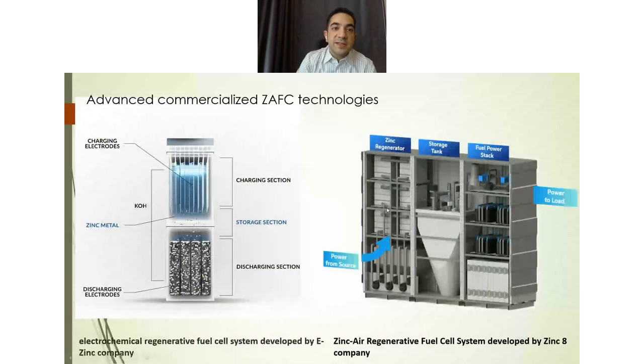There are some advanced commercialized zinc fuel cell technologies with different ideas of operation. The one on the left, developed by E-Zinc company, is using the charge electrode on the top side to regenerate the zinc metals, and the zinc metal, under the effect of gravity, will fall down to the bottom chamber in which the discharge electrodes are present, and they dissolve back into the electrolyte during the discharging, and then due to the concentration gradient they will move up again to the top section.